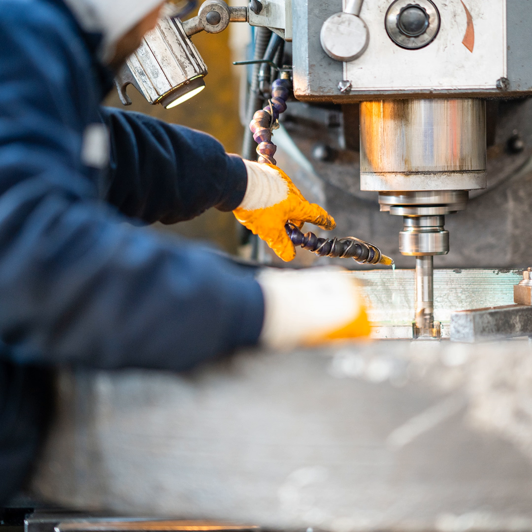But when we look at an HEM machining, you can go 355, I've actually gone up to 400 on titanium and milled it quite effectively, based on a 5 thou chip load. Essentially that's going to give us just under 3.5 thou chip thickness, which is really kind of ideal to have. And you can see the huge difference in the cubic inch removal, the metal removal rate, jumped from 2.1 to 6.4. So there is a significant increase of productivity.